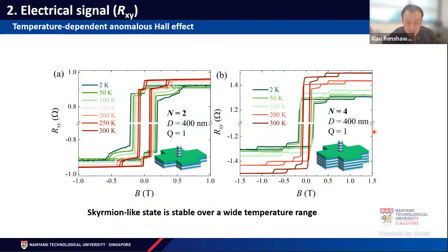Then, of course, we move a little bit one step further. So we also check whether it's stable over a wide range of the magnetic temperature. Of course, when you go down to the low temperature, we see it's stable over a very wide range of the temperature. Of course, ideally, we also go to the higher temperature, but due to the limitation of our research capability, we cannot go even higher. So we only go up to 300 Kelvin, but from a fundamental research point of view, it gives us a little bit of insight on the parameter or the strength of the magnetic interaction.